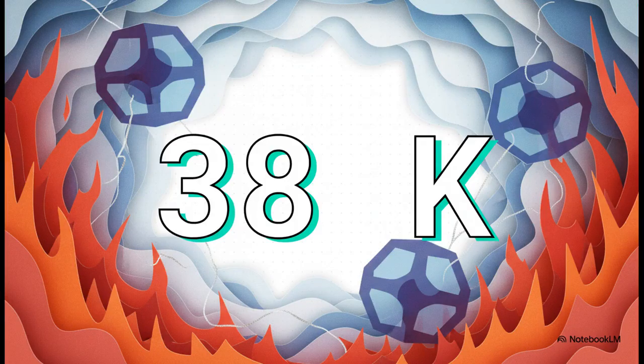Now, despite decades of really intense research, 38 Kelvin is the absolute highest confirmed transition temperature achieved so far in these organic materials. Specifically, that's in cesium-doped fullerenes. Just to put that into perspective for a second, 38 Kelvin is about minus 390 degrees Fahrenheit. That is literally colder than the surface of Pluto. So clearly we're still quite far from Little's ultimate dream of a room temperature organic superconductor.